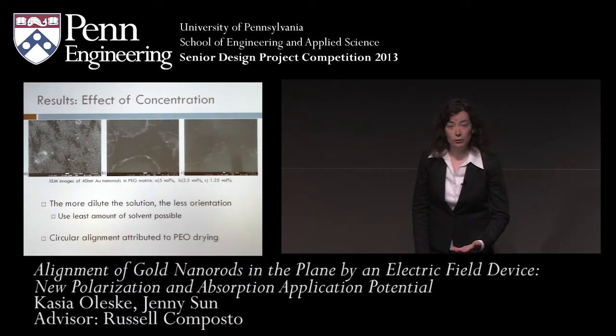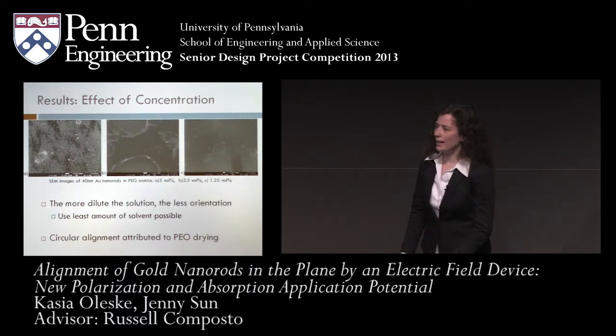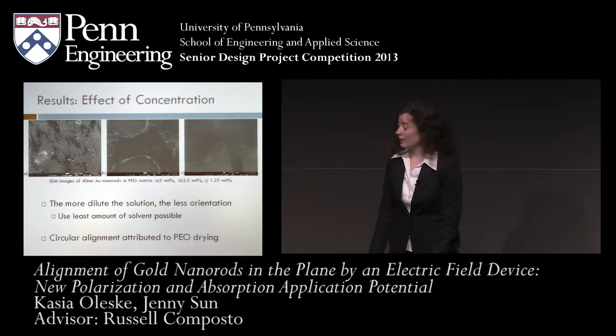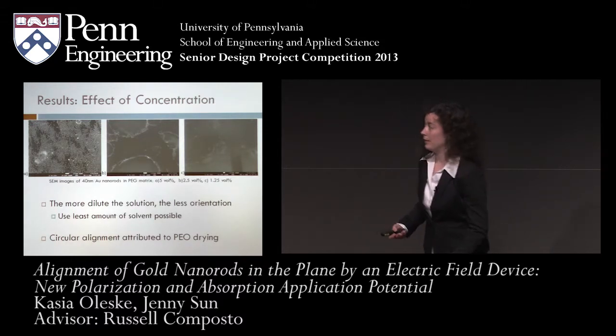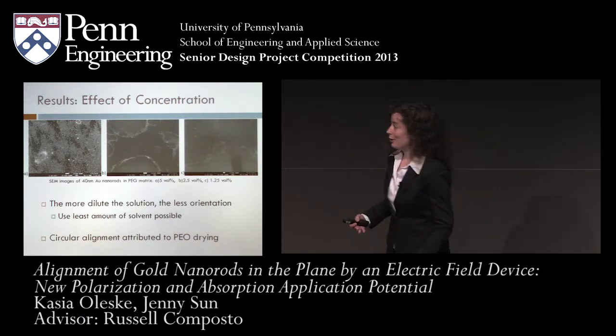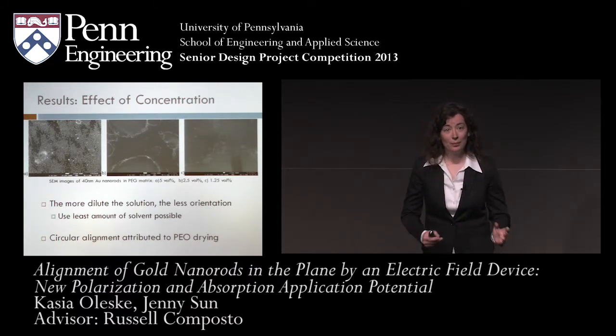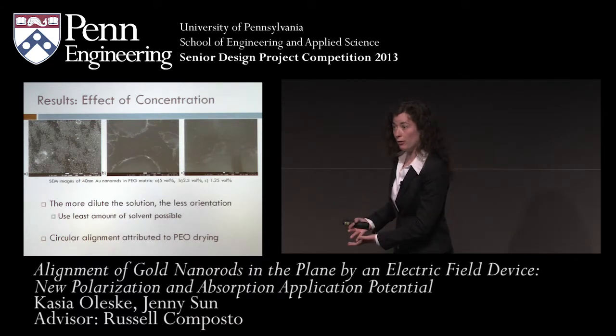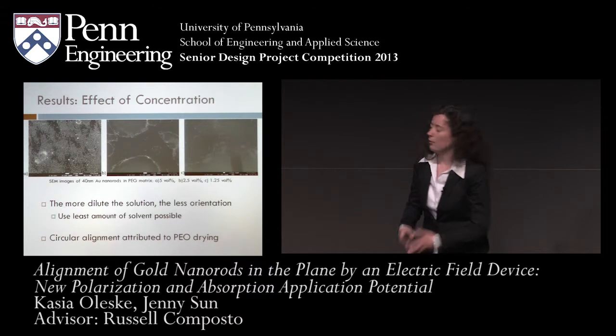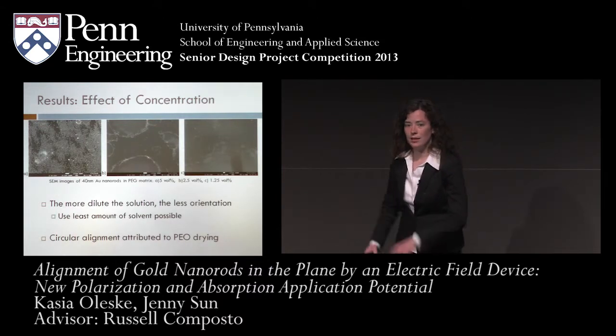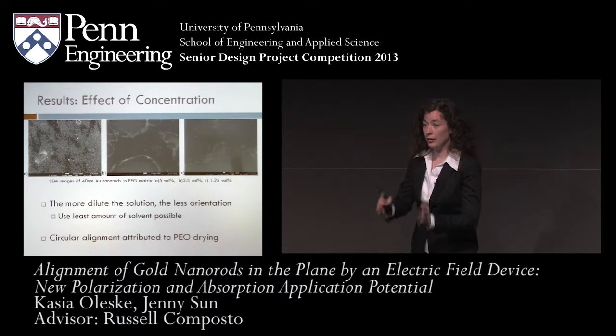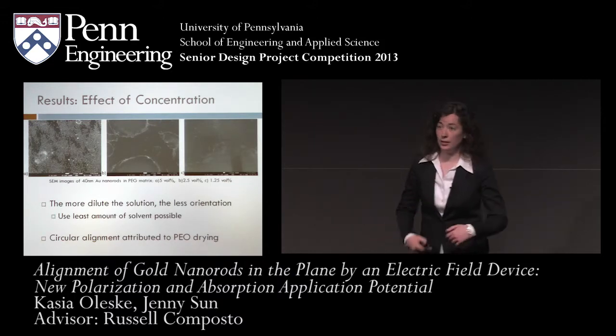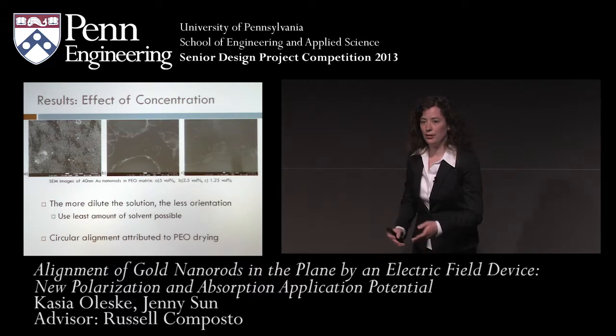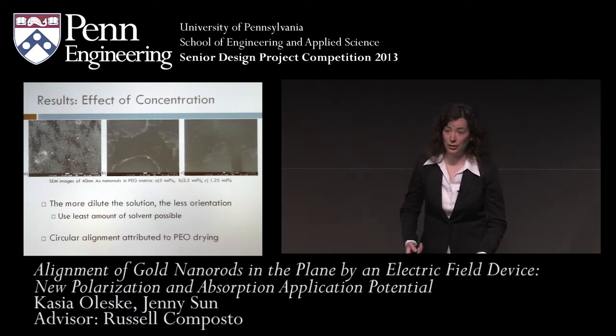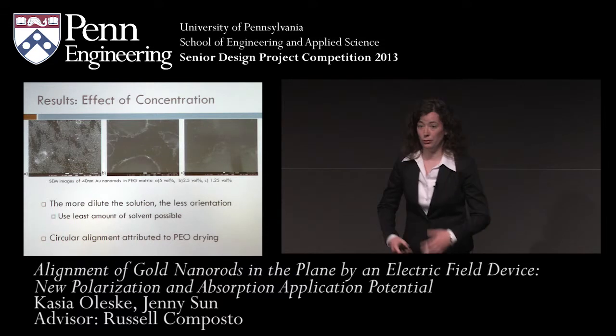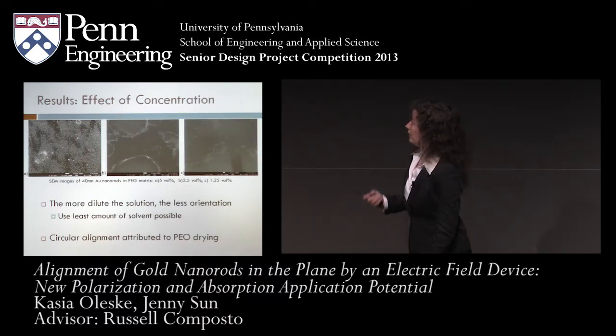One of our other studies we did was a concentration study. We wanted to find out, should we have more or less solvent in order to get increased alignment? So the short answer to this question is we want to use the least amount of water or whatever solvent you want to make these samples in order to get the best alignment. This makes sense because in order to get alignment, you're orienting the gold nanorods. And if there's increased solvent, they can just float around and there's more time for evaporation, which is what we relied on in order to lock the gold nanorods into place.